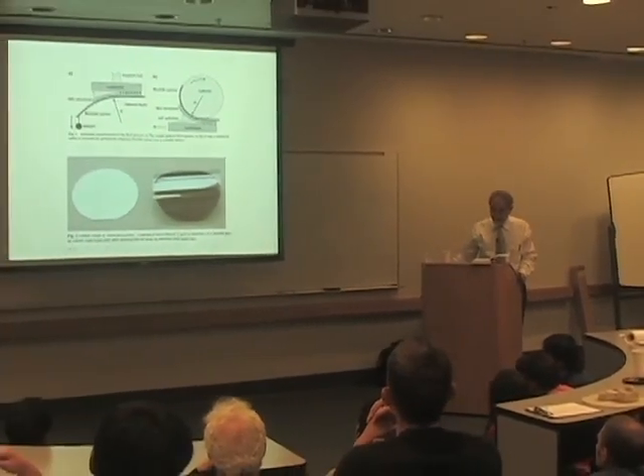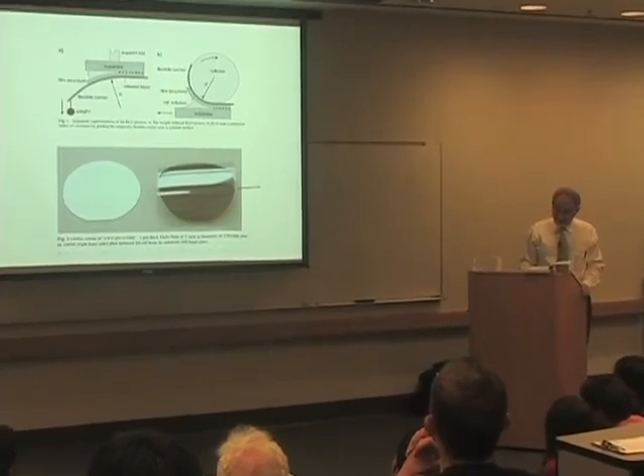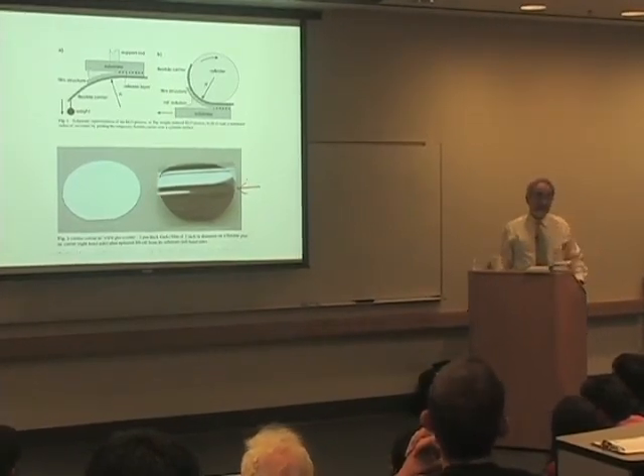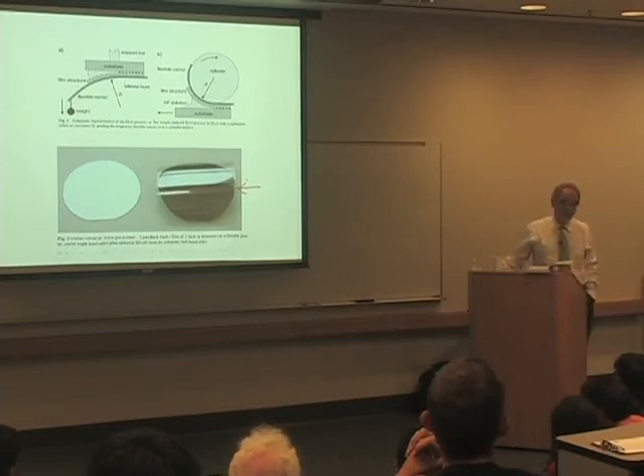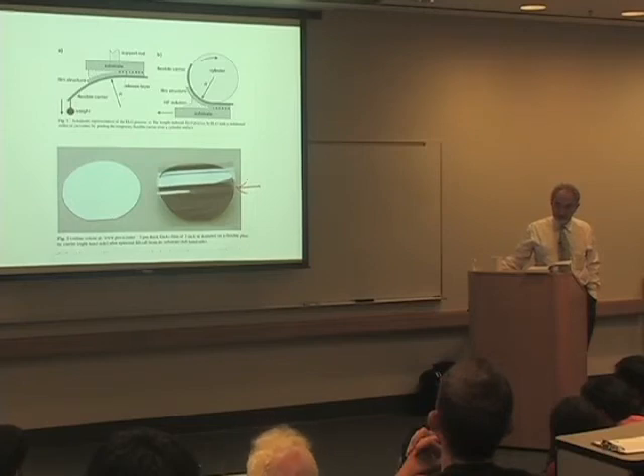There are now emerging several ways of making thin crystalline films at low cost, peeling methods. They now have a method of peeling thin silicon off of a boule of silicon. So the improvements are going to be there. This is what the gallium arsenide looks like. You lift it off. This was published by a group in the Netherlands about 15 years ago. There are many ways of doing this, so I don't say we're necessarily doing it this way. But you end up with thin films, quite flexible like this, and you just work with them. And the cost projects out to be extremely low, to the degree that the cost of the panel, I think, will end up being less than the cost of mounting the panel in the field.